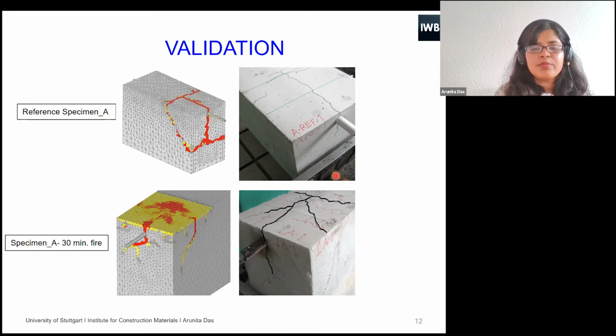These are the reference specimens which were not subjected to fire, and these are the specimens which were subjected to fire. Here also we can see the splitting failure. So instead of pull out failure, we are getting splitting failure, which is restricting the bond capacity. And this can be explained only by the temperature gradients.